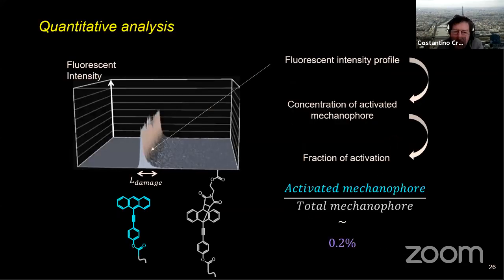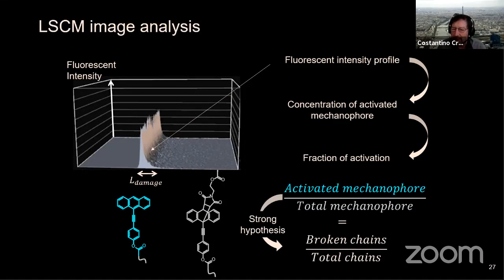Now I go to the next assumption, which is maybe the most important one, and I'll be welcome to field questions too. The representativity. What we measure is a fluorescent profile, and this gives us a concentration of activated molecule. That's directly the measurement. Now the question is the activated mechanophore relative to total mechanophore; we measure things in less than 1%, a very typical measurement where we are really well within the detection limit. But what we really would like to know is how many polymer chains have broken, not just how many mechanophores. So we would like to say that this ratio is the same as the ratio between broken chains and total chains, so that the probability of breaking your mechanophore in the network is the same as that of breaking a stronger carbon-carbon bond in the network.